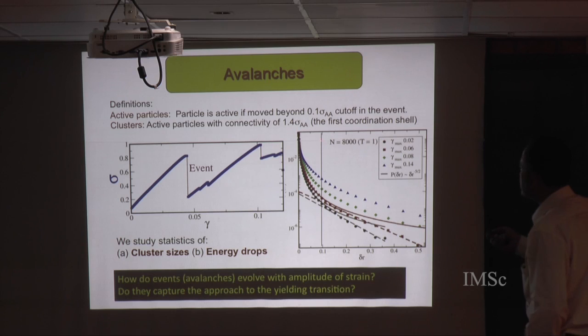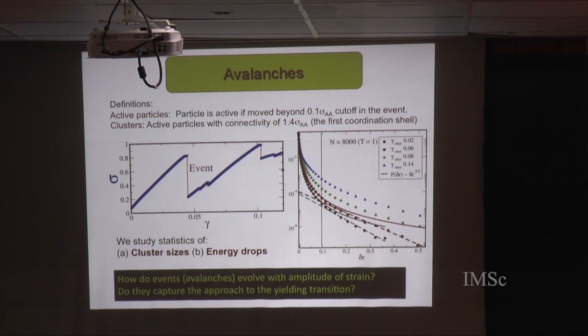But one has to do what one can, so we use a reasonable cutoff of 0.1 sigma as separating the active particles at larger displacements from the particles sitting in the power law tail at smaller displacements.